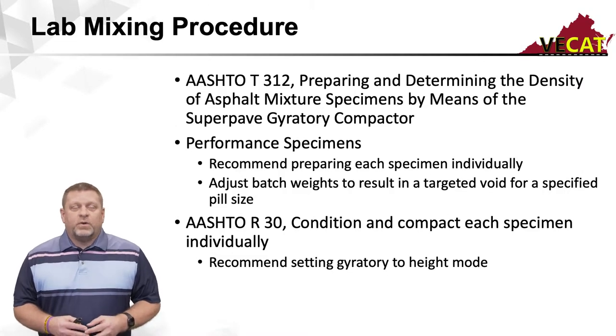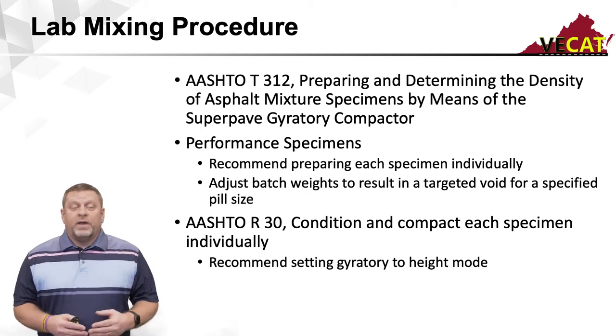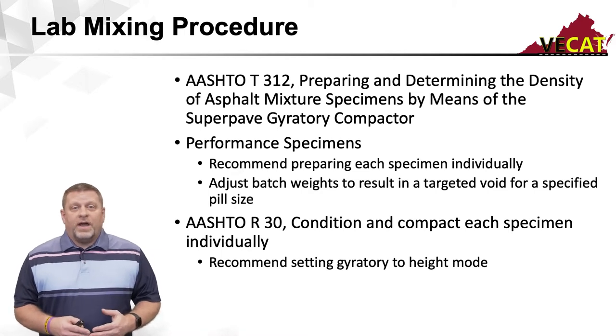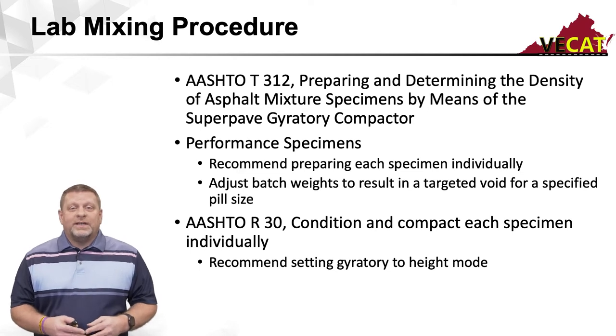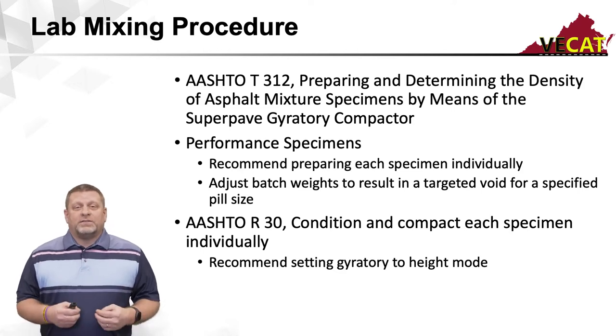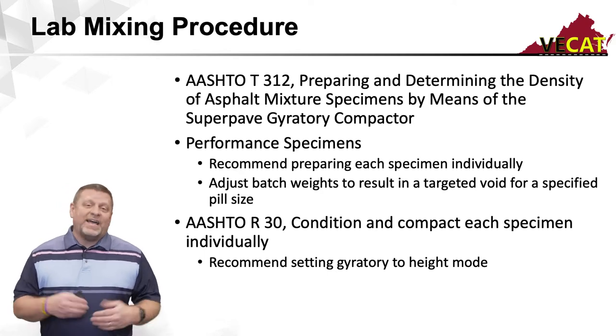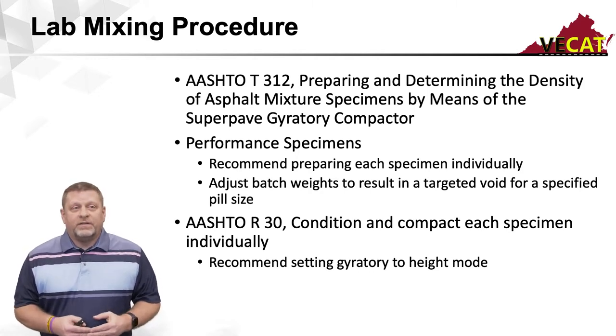The lab mixing procedures, whether you're making BMD or performance test specimens or volumetrics, haven't changed. You still follow AASHTO T312 on how you prepare the specimens. For the performance specimens, it is recommended during the mixing procedure that we prepare these specimens individually. We want to avoid adding variability during the mix design phase when batching and mixing, so we recommend these be done individually.